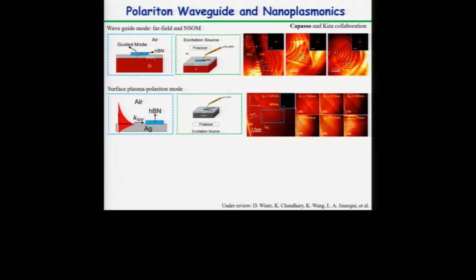There are ripples on each of the samples. This is a triangular circular sample, and they can look at the wavelength. In plane, when they are collecting using an optical fiber moving across the sample, they can look at what is now the wavelength on the sample, and based on the difference from what you are exciting with and what you are collecting from, you can obtain the refractive index of boron nitride.